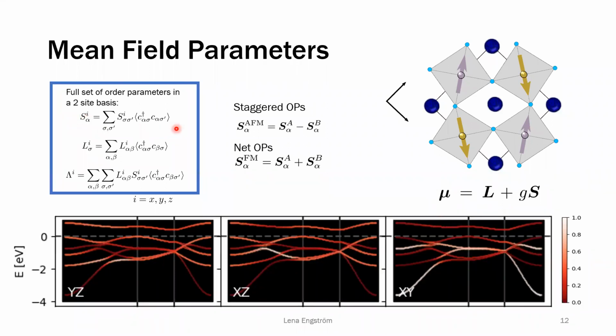What's interesting is that, since we have several orbitals, we can have contributions from each of the orbitals. The spin arises from different spin within the same orbital, so we can have three different spin order parameters. But we also have this angular momentum, which is the same spin but mixes orbitals. And since we have a strong spin-orbit coupling, we also need to include some order parameters that mix both of these components. And since we have a two-site basis, and we expect a canted antiferromagnetic state, we want to consider two sites that are independent. So we could have some staggered order, that is the difference between sites, and some net order, which is a net moment in some direction.